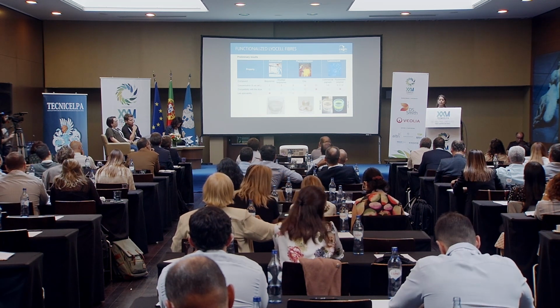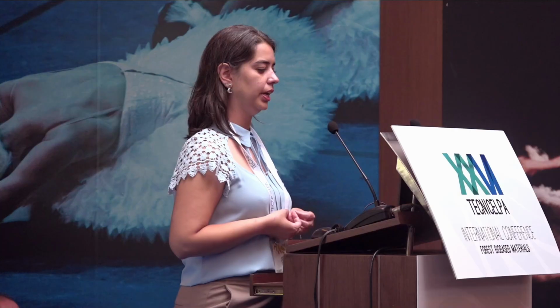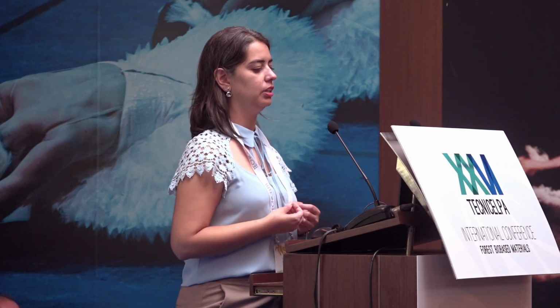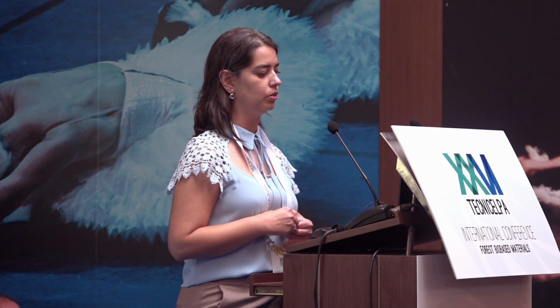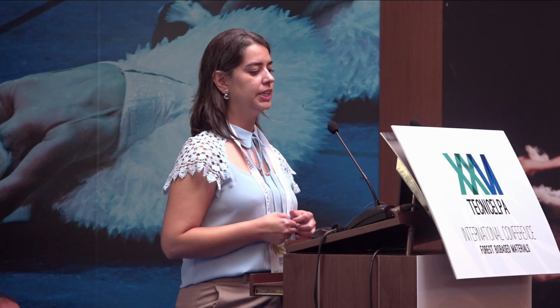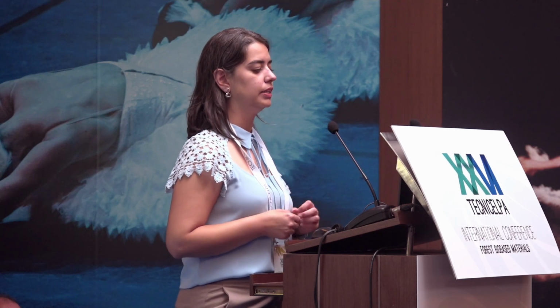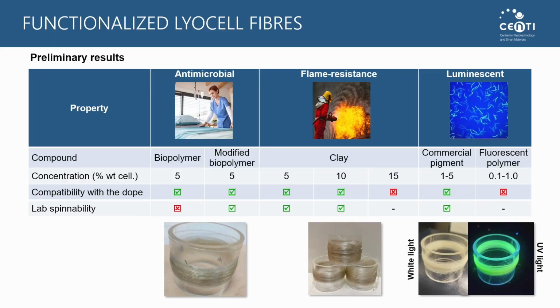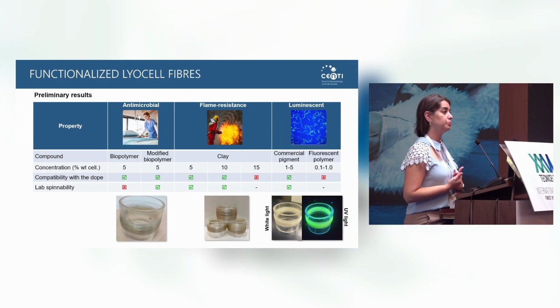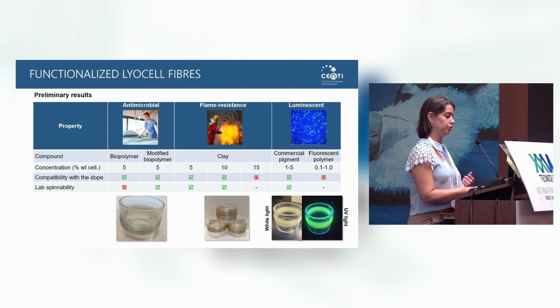For the flame resistance, we used a clay, a commercial clay, and the best concentration was 10% based on cellulose. For the luminescent properties, we also tried two pigments: one inorganic commercial pigment that was adequate and suitable for the spinning process and dissolution, and also a fluorescent polymer that is also commercial, but it was insoluble in the dope solution, so we did not follow with that.